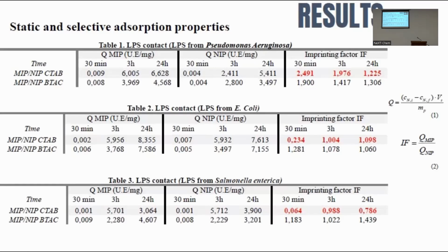The difference between the MIP-CTAB and BTAC imprinting factors may be due to the presence of a larger number of cavities formed in the polymerization stage for the CTAB system. The decrease of the imprinting factors over time for both systems may signify the presence of a non-selective absorption: the rebinding of LPS in the specific cavities with a similar shape, but also the rebinding of the LPS on the surface of the particles through other physicochemical interactions.